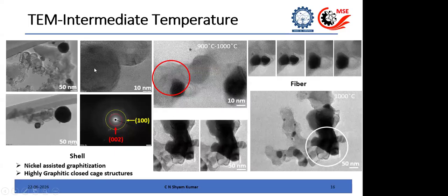One thing that we need to keep in mind here is that the nickel particles are not exposed to the atmosphere, but are covered with graphitic carbon. So what you have is small nickel particles, which are covered by a few layers of graphitic carbon. So you have a core shell structure. So this is with the microstructure.